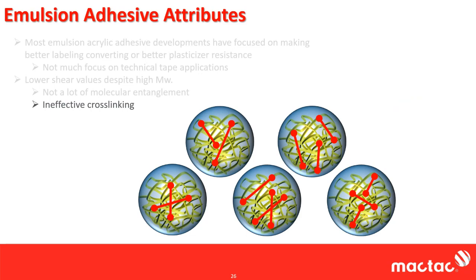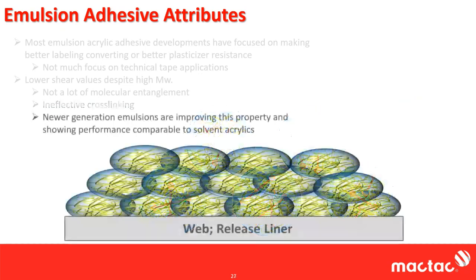But it does increase the cohesive strength a little bit, though you're never going to get that cohesive strength up to where the solvent-based and the UV adhesives are, mainly because you're getting a lot of cross-linking within the micelle, but the micelles themselves aren't really interacting. Now, I will say, with very recent developments, you're starting to see newer generations of emulsions improve this property. As things are coalescing onto the web, you do get some interaction and cross-linking between those micelles. And because the cross-linking can occur between micelles and these conglomerates of polymers, you're starting to see more and more properties comparable to solvent acrylics and UV acrylics.